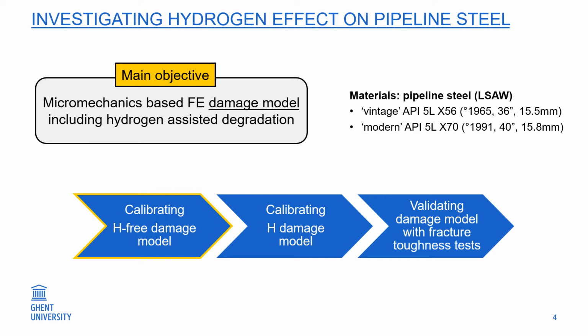Our approach can be divided into three steps, the first step being calibrating a hydrogen-free ductile damage model. The second step is adapting the model to include the physics of hydrogen transport and capture the accelerated failure. The third step is to validate the calibrated models with fracture toughness tests. This project was recently initiated and I will discuss only the first step here, how we are going to calibrate the damage model which doesn't include hydrogen.